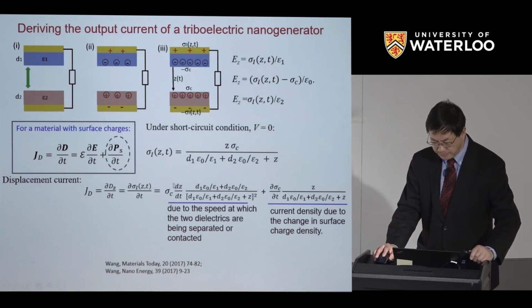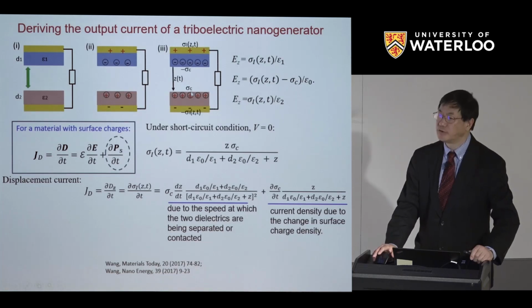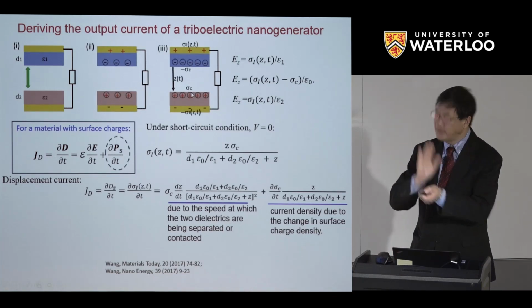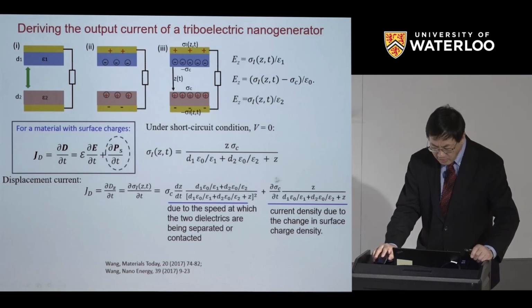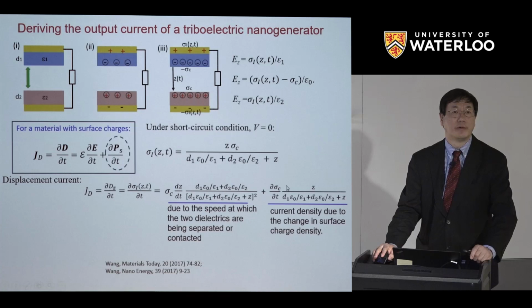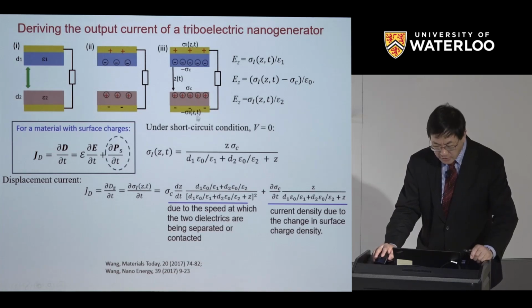The first term is dz/dt. Z is the gap distance between the two media. dz/dt is the speed at which they contact, so the speed at which you make contact. The faster the speed, the better. Okay. The other one is the rate of the surface charge buildup. So that means the rate at which the surface charge increases here.